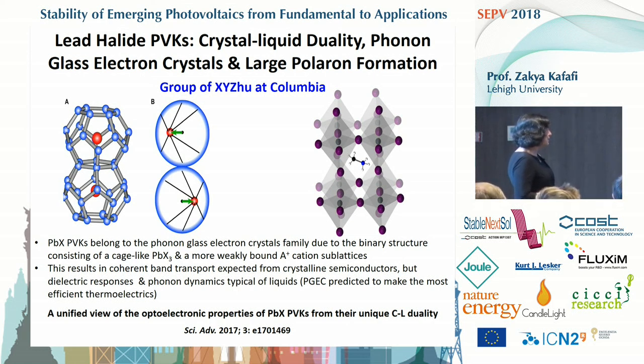These materials belong to phonon-glass electron-crystals, and so the binary structure consists of a cage-like lead halide and a more weakly bound cation sublattice. This results in coherent band transport, which is expected for crystalline semiconductors, but dielectric responses and phonon dynamics typical of liquids. And these materials show promise to be efficient thermoelectrics.